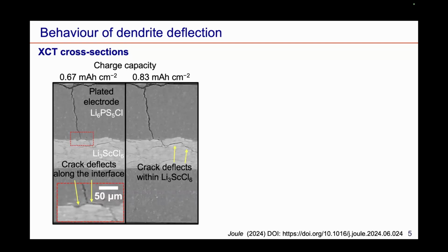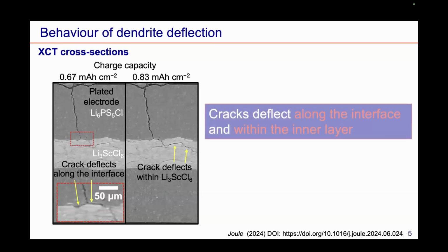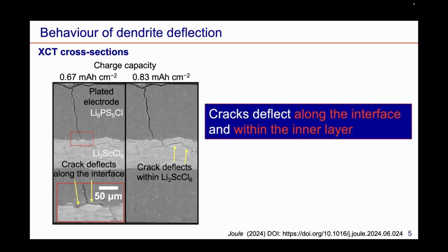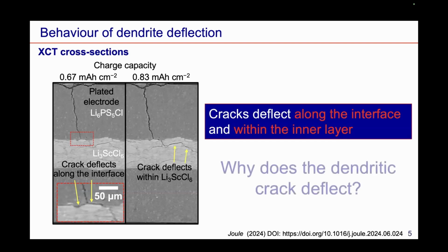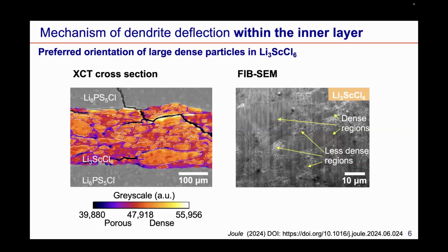We can observe that the dendritic crack firstly deflects along the interface between the two different layers, and then it enters the inner layer, where it is further deflected within this inner layer. Now the question is, why does the crack deflect along the interface and also within this inner layer? First, let's consider the deflection within this inner layer.